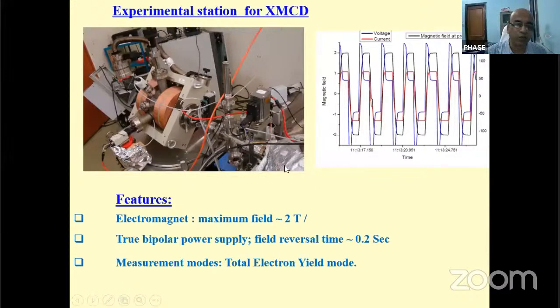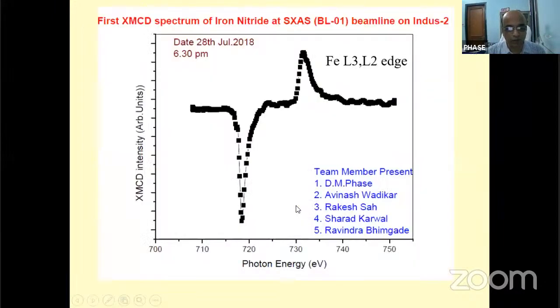Basically, instead of doing the left circular or right circular, one can change the direction of the field. So here we are keeping the beam fixed at one position of left circular, and we are changing the magnetic field direction. This way, a 2 Tesla magnet is put inside the chamber, and then we have collected this XMCD spectrum.